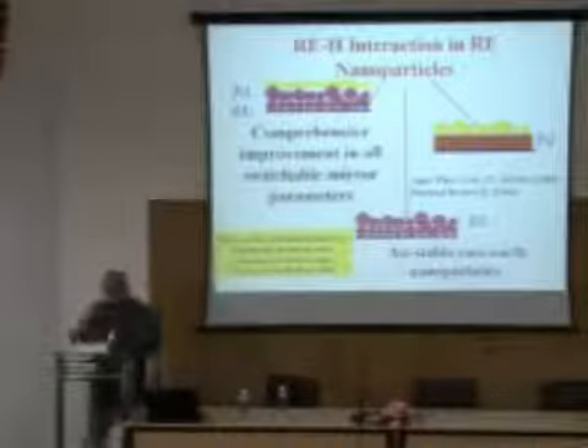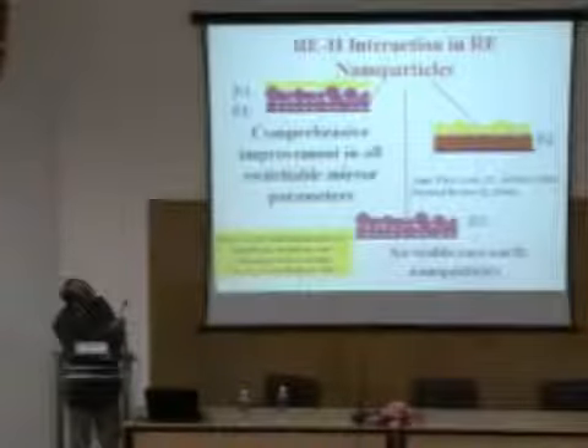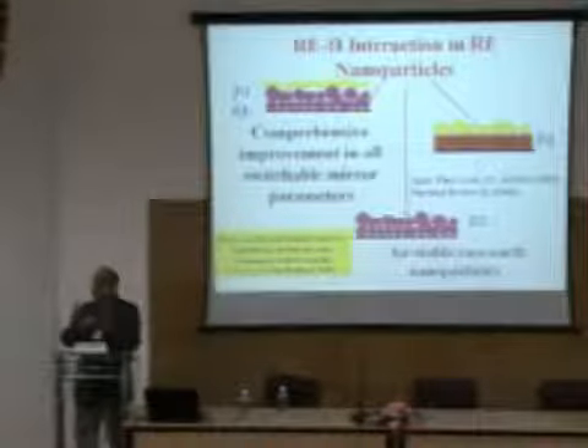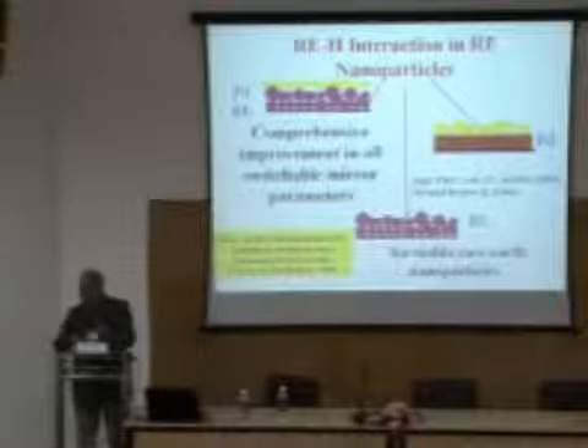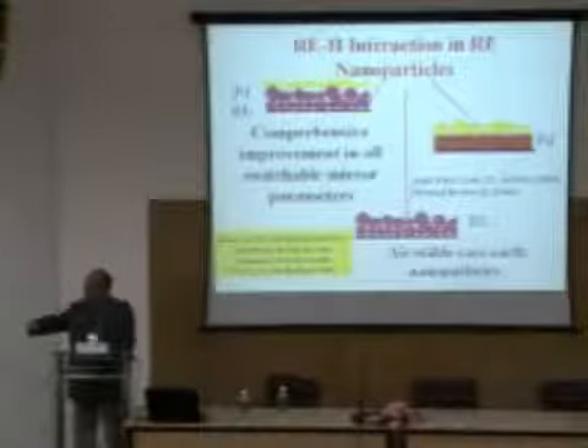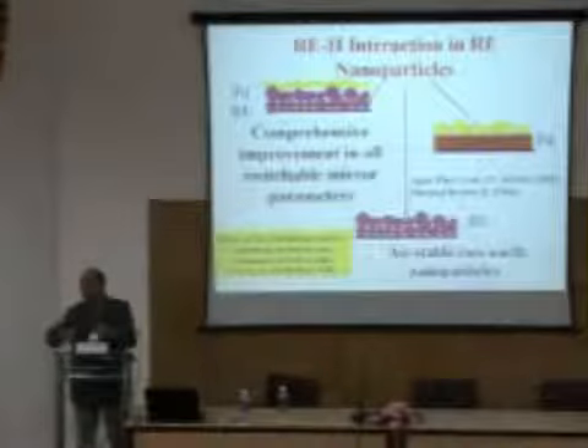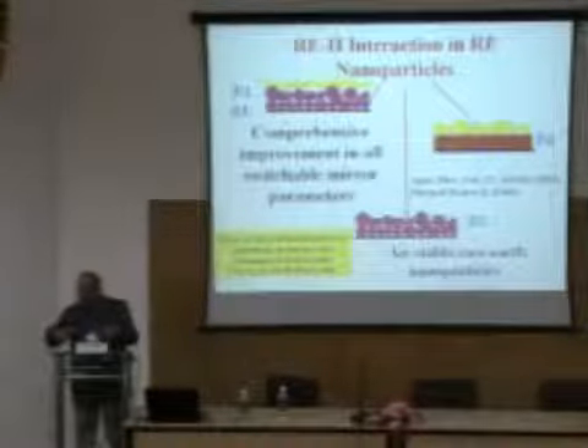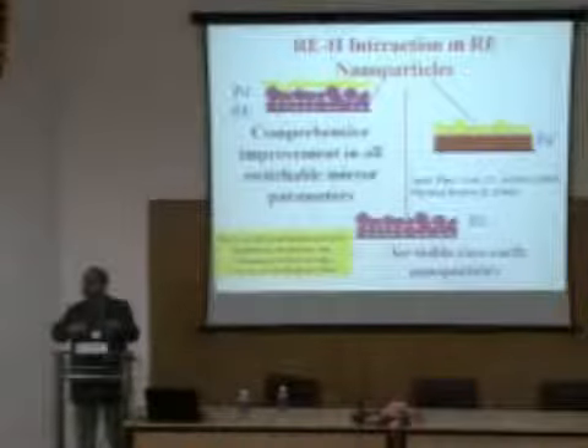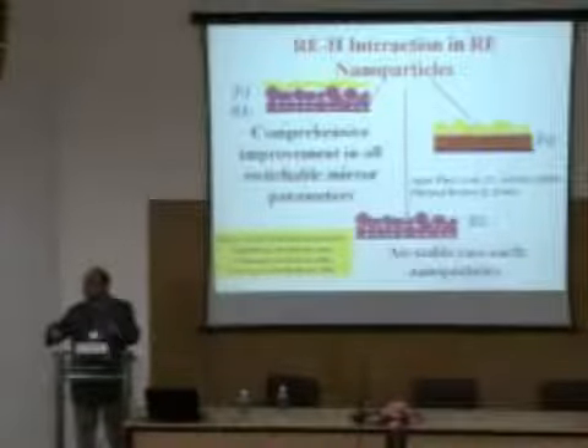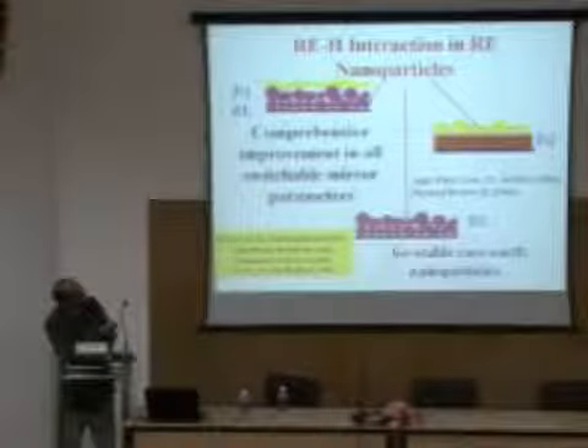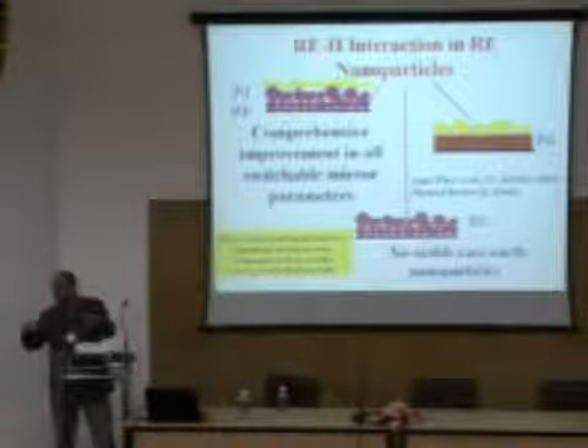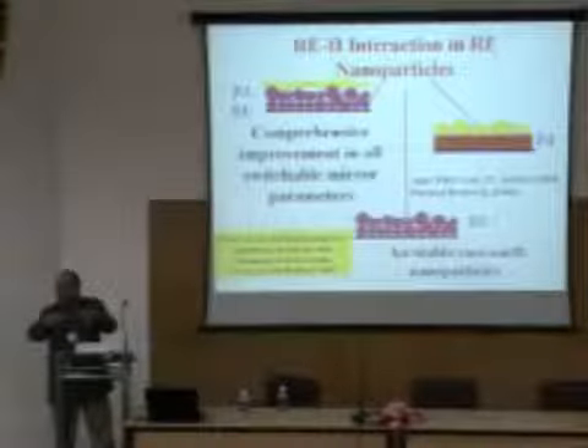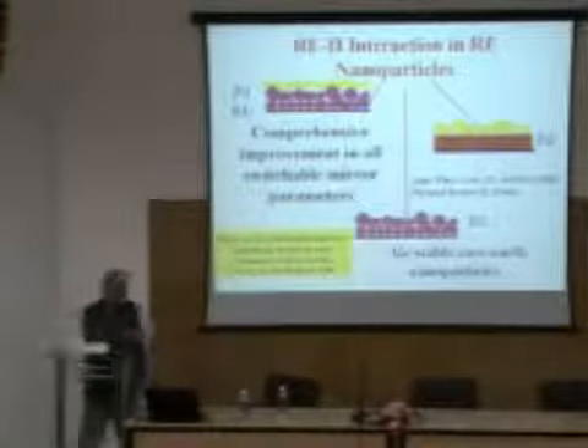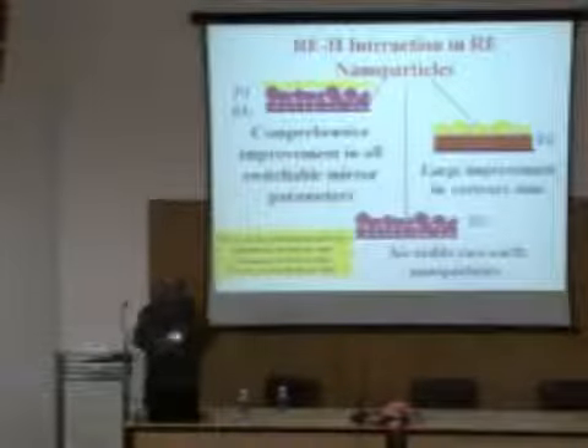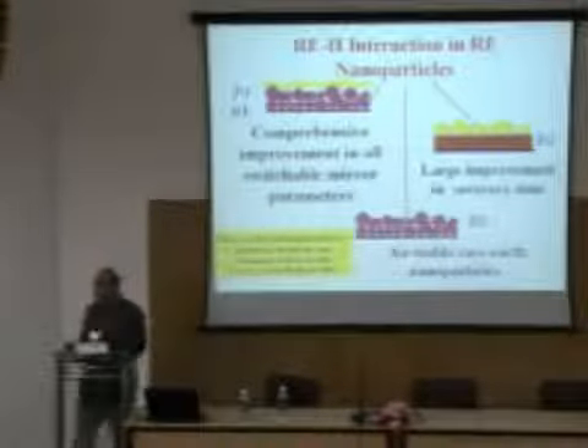Then the third system which we investigated was palladium, because palladium also is very important. As I already mentioned, palladium plays the role of a catalyst, and the catalytic reaction takes place at the surface. We thought it's obvious that we should change the palladium overlayer and bring in a palladium nanocrystalline layer, so as to increase the surface area and increase the catalytic reaction. So to investigate that effect, we kept the rare earth material as a thin film and made the palladium overlayer a nanocrystalline layer, and we observed that there is a large improvement in the recovery. Recovery time I will describe later.